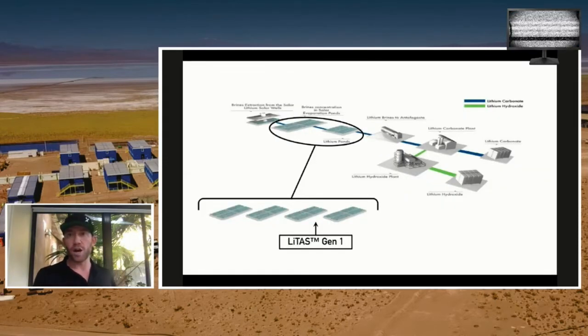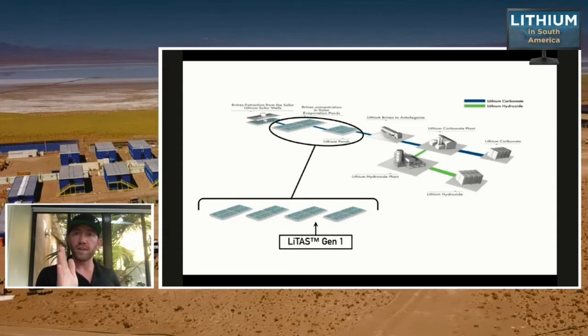So what EnergyX's complementary technology looks like is this. We insert ourselves mid-pond sequence, typically after the third pond. The reason we come in at this point is we want to come in right before the lithium magnesium co-precipitation. Now, if you look at brine compositions between Chile, Argentina, and Bolivia, the three countries that make up the lithium triangle, they all have somewhat different brine chemistries. We're typically focused on high or mid magnesium brines, which is not that prevalent in Argentina, but there is still some. So we want to come in right before the lithium magnesium co-precipitation.